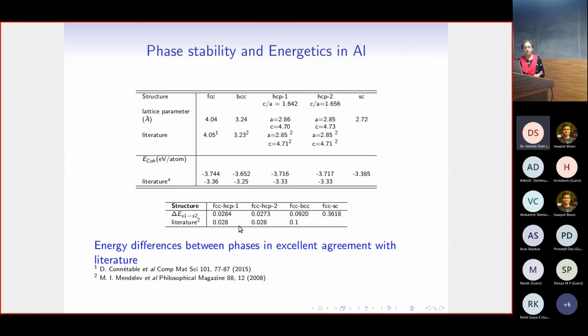From the energy stability perspective, I should be able to predict from a particular potential which is going to be the most stable phase for that particular material, and which are going to be energetically less stable phases, and what is the difference between those phases, which determines the stability. So this we see we are getting good agreement. This is a very nice thing.